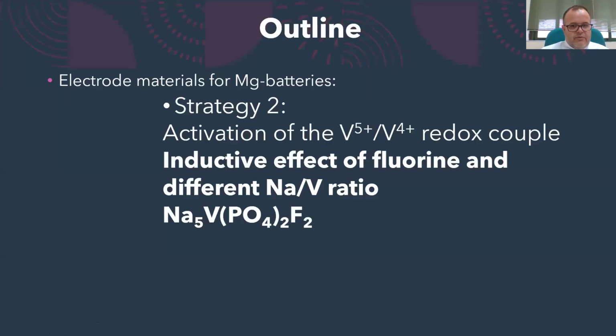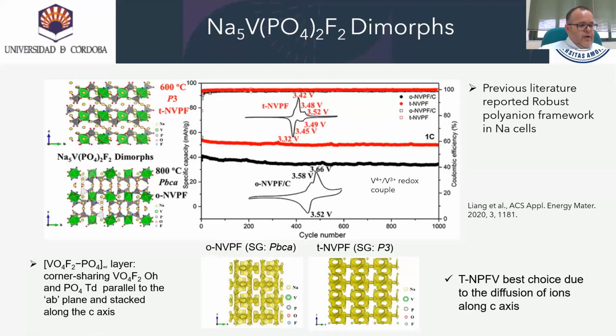Strategy number 2 consists of the activation of the vanadium 5+, vanadium 4+ redox couple and the use of the inductive effect of fluorine, using different sodium to vanadium ratios in Nasicon type compounds, such as sodium 5 vanadium 1 PO4 2 F2. The use of fluorine in sodium vanadium phosphate with different vanadium to sodium ratios is studied in the dimorphs of this composition.